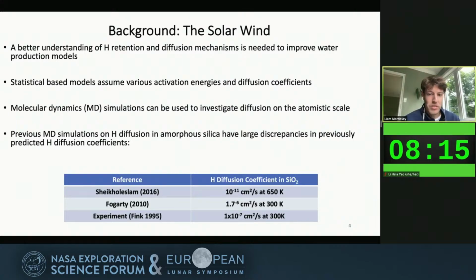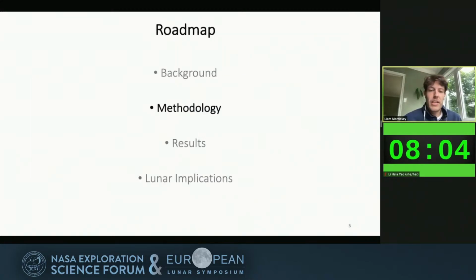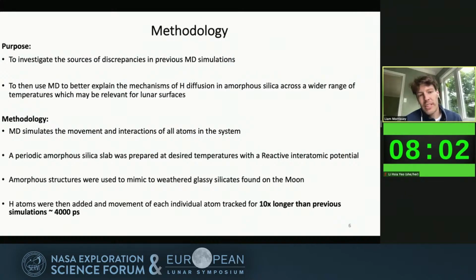And this is a problem because if we want to rationalize that we can use MD, we're going to need to rationalize why we're seeing such a large range in predicted values for simulations that look very similar. So basically what our purpose was, we wanted to investigate the source of these discrepancies in previous MD studies. And then after doing that, we wanted to use MD to better explain the mechanisms of H diffusion in amorphous silica across a wider range of temperatures, which may be relevant for lunar surfaces.